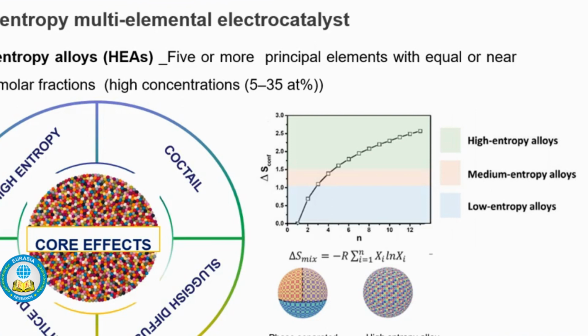Their synergistic effect carries unique properties which are expedient for catalytic oxidation reactions, and the catalytic activity of this material can be boosted by tuning the composition by combining more catalytically active elements, as well as tuning their phase structure into intermetallic compounds, solid solutions, amorphous phases, or a combination of those phases. Amorphous multi-elemental materials are significantly unexplored. However, their dissimilar elemental interaction could offer access to new emerging properties.